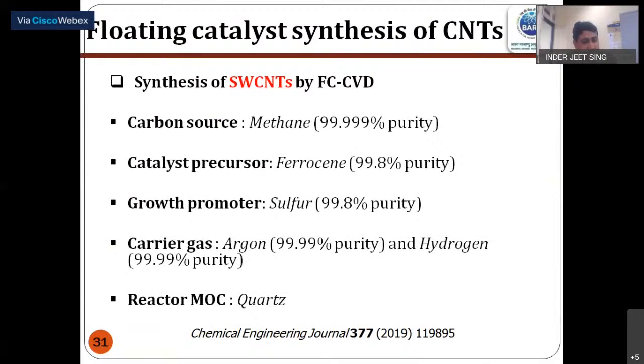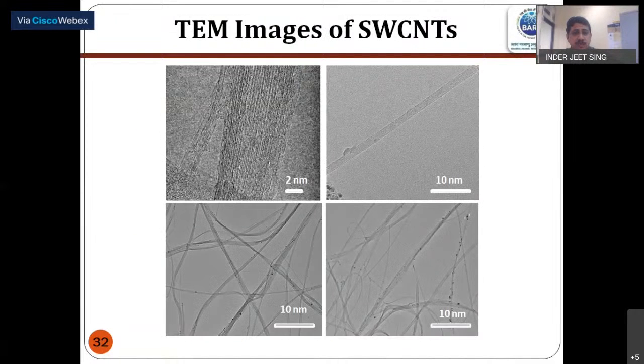And if we talk now about the single wall carbon nanotube, generally another process is followed, which is called floating catalyst chemical vapor deposition. So there we use methane, because why methane? Methane has a single carbon molecule, so controlling the carbon is easy in methane. Then ferrocene is once again used as the catalyst. Then another important material, sulfur, is required for the growth of the single wall carbon nanotube. And then argon and hydrogen. The hydrogen and sulfur, these are the two important factors. So hydrogen controls the kinetics and decomposition of the hydrocarbon, which is very much required for the growth of the single wall carbon nanotube.